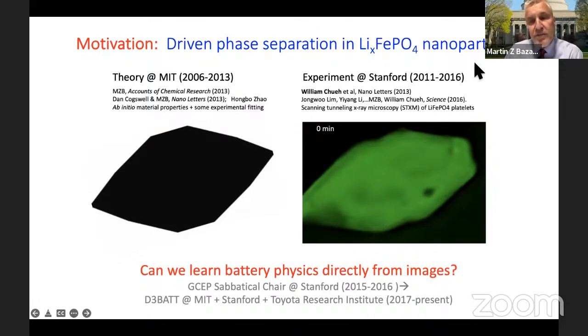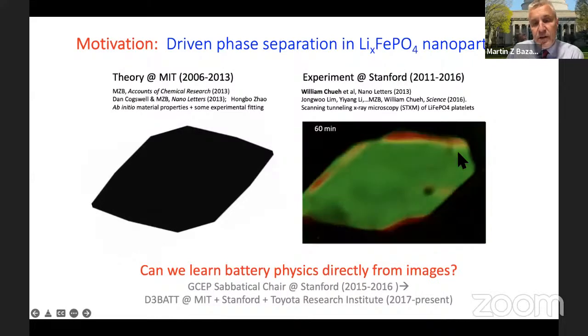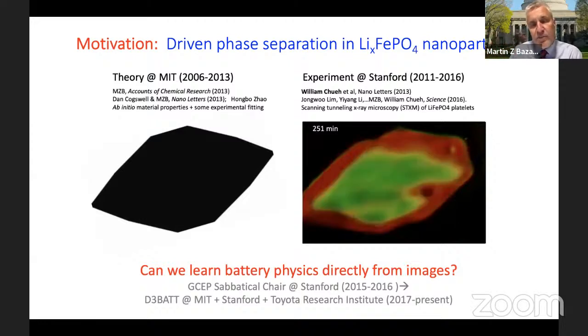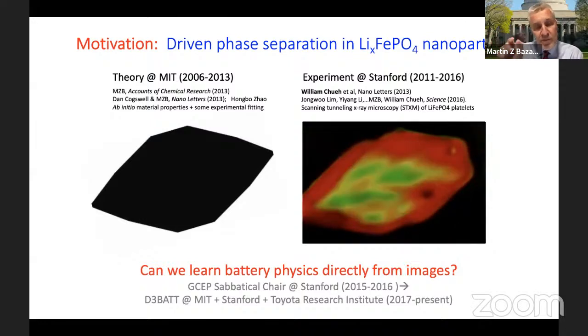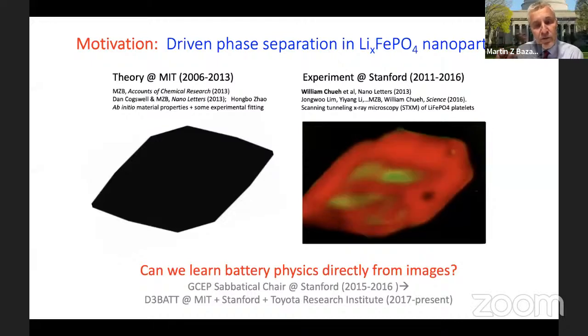And I went on a sabbatical to Stanford in 2015 and 16, and by that time, William Chueh's group was able to extract images like the one shown here, which are images done by X-ray scanning transmission microscopy, STXM. So basically, with about 5 nanometer lateral resolution in every pixel, the X-ray goes through the particle, which is a platelet of about 100 nanometer thickness and 1 micron across. And as the battery is operating in a certain electrochemical cell that goes into the synchrotron, you can actually see the dynamics of lithium going in and out of every individual particle in that system. And so we have this set of images.